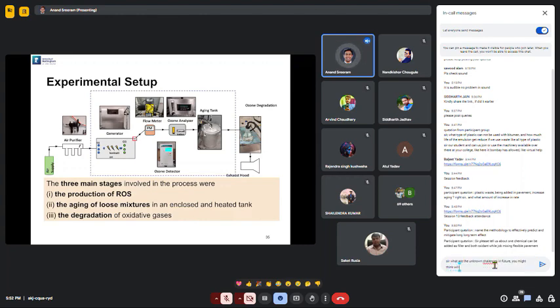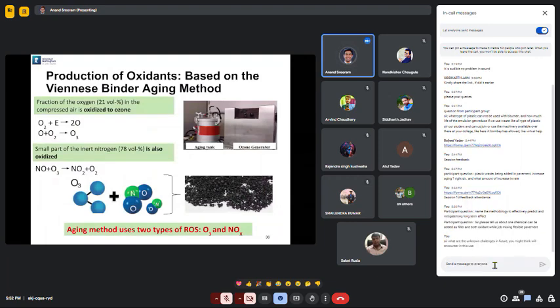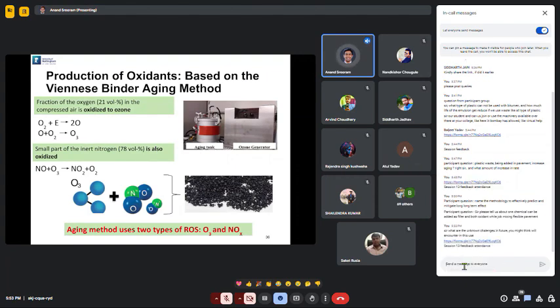Then the aging of the loose mixtures in an enclosed and heated tank, and lastly, the degradation of the oxidative gas. This was essentially based on what we call the Viennese binder aging method. We used air, and then we used an ozone generator to produce what we call reactive oxidation species. These reactive oxidation species really help to increase the rate of oxidation, and that's what we saw in this study.